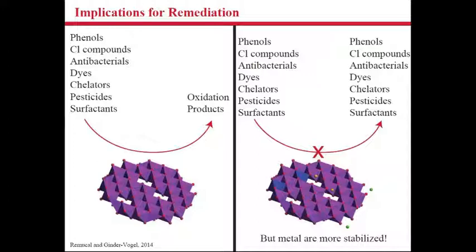I completely agree with you. There's a paper where they did quick X-ray spectroscopy on cobalt, and cobalt tends to go into manganese oxides. Basically, it goes from cobalt 2 to cobalt 3. Cobalt 3 is exactly the same size as manganese 4, and it tends to just end up in the hole where the manganese oxide was, so it fills that hole.